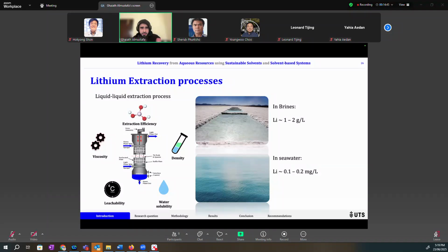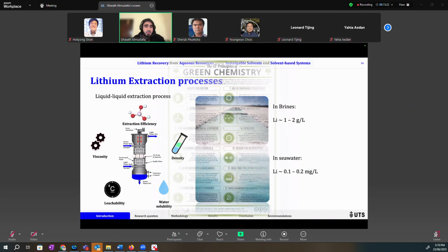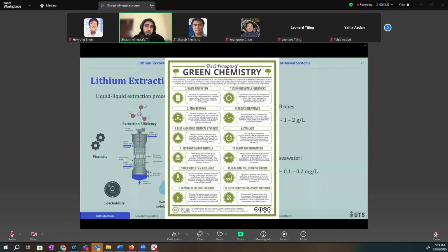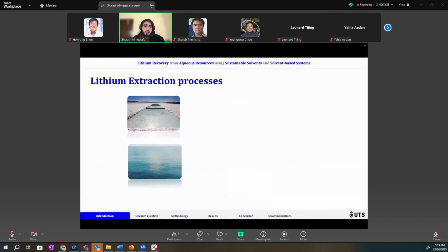Now, again, going back to the aqueous resources, it's not one size fits all, it's a case by case. If you're looking at brines, you have high concentrations, 1 to 2 grams per liter. But if you're looking at seawater or even industrial water, you are looking at much more diluted levels of lithium. Diluted levels of lithium means a huge volume to be processed. Here's where I'm going to mention the different processes for lithium extraction. Solvent extraction is not the only one that can be used for recovering lithium.